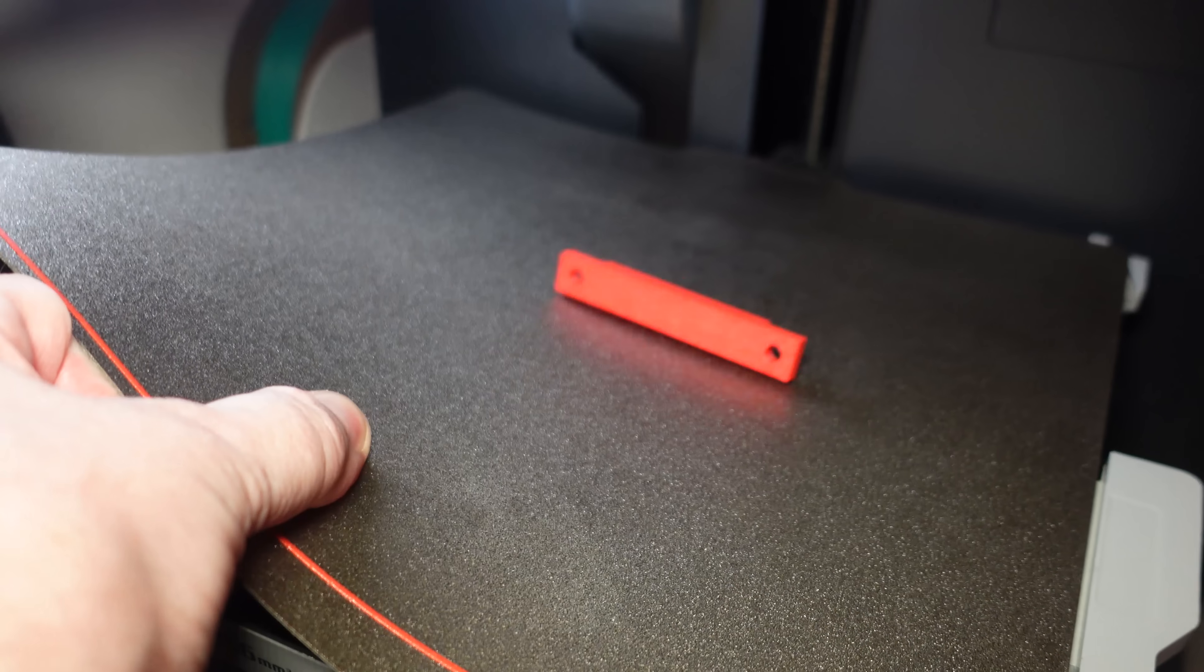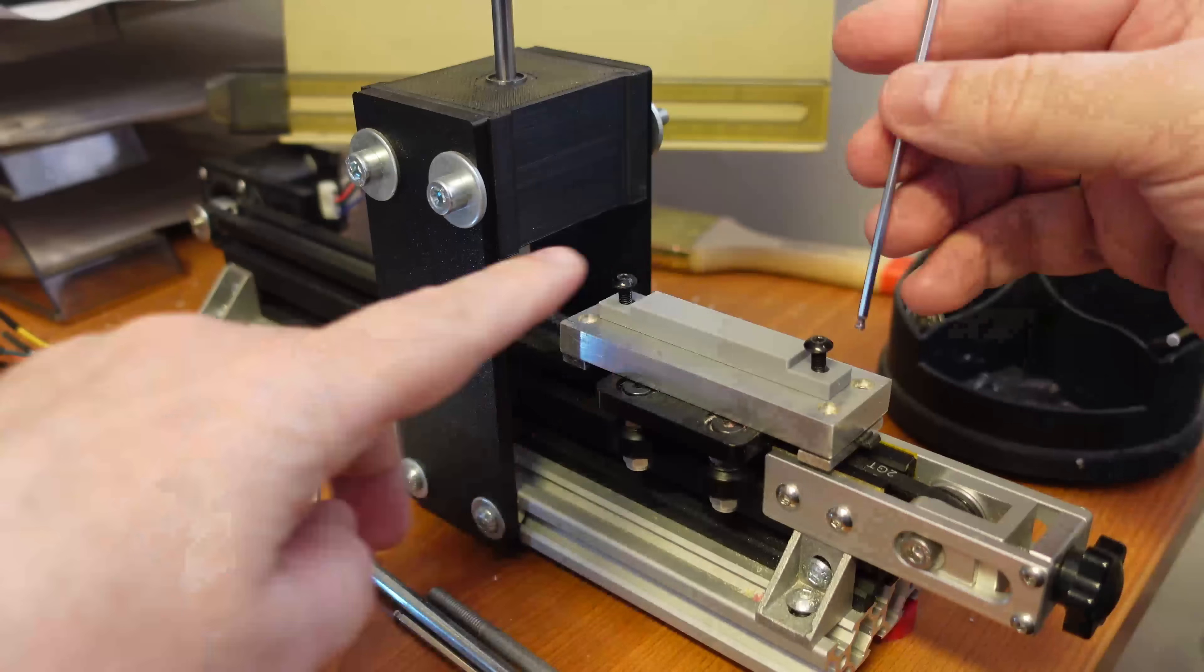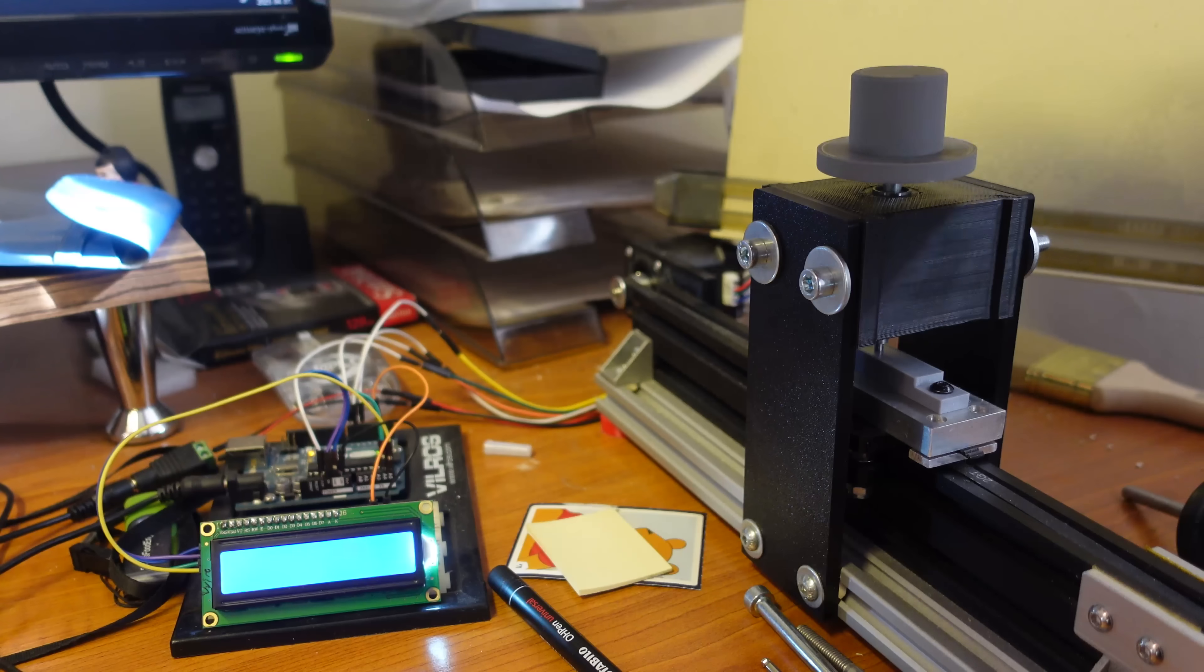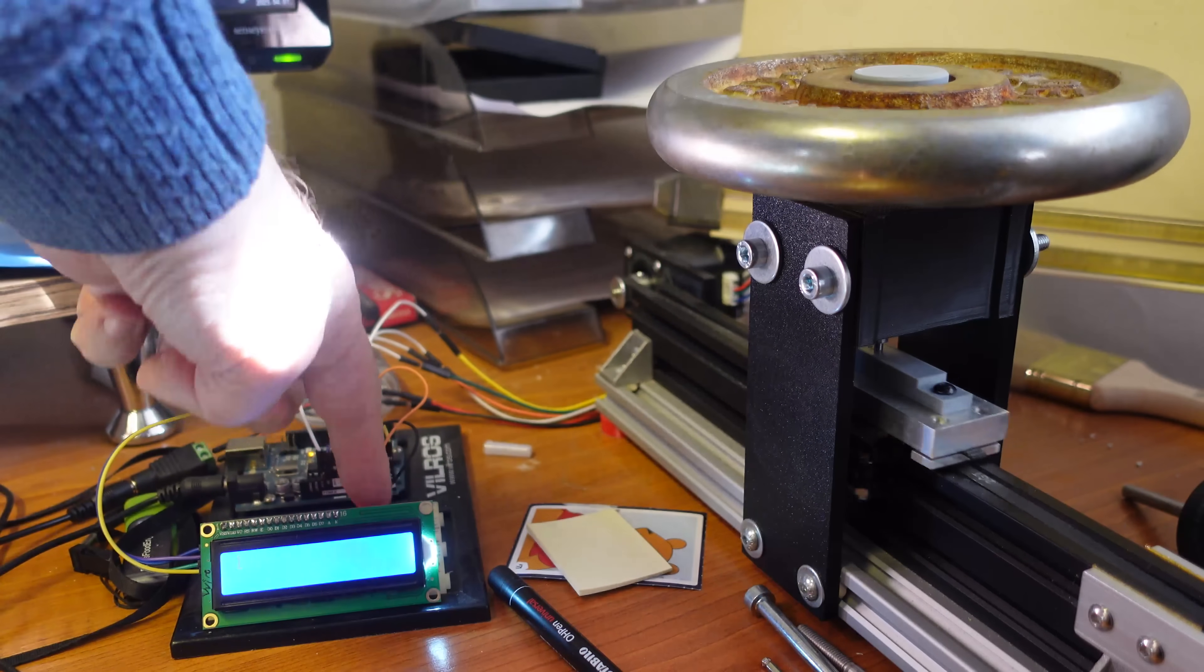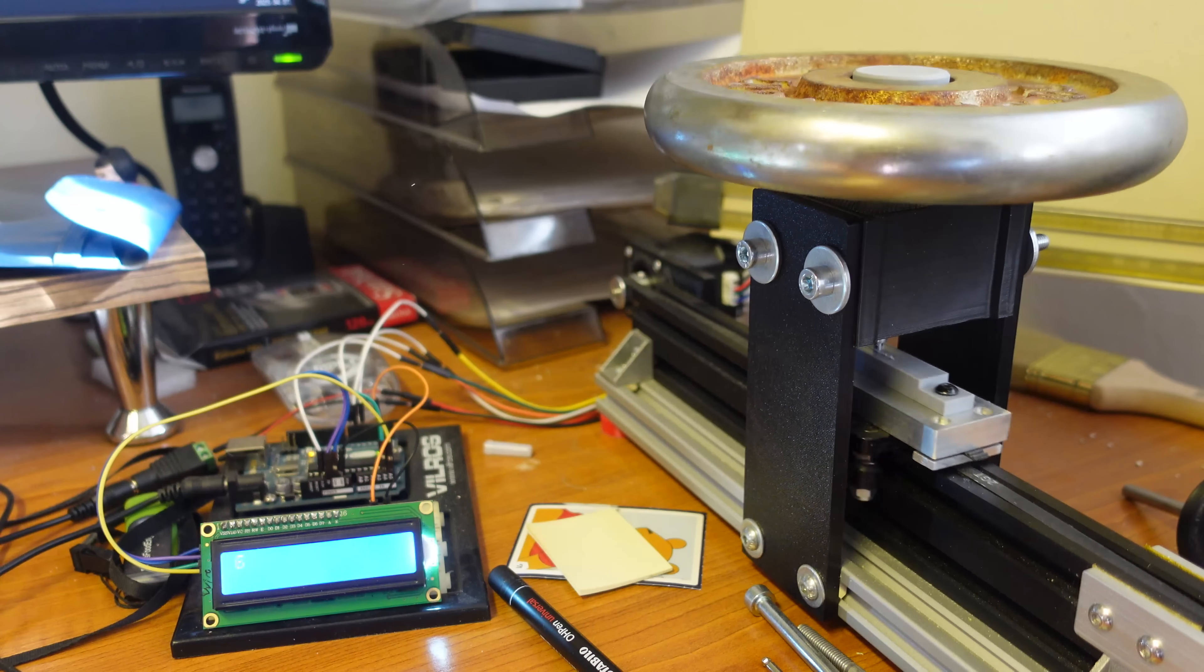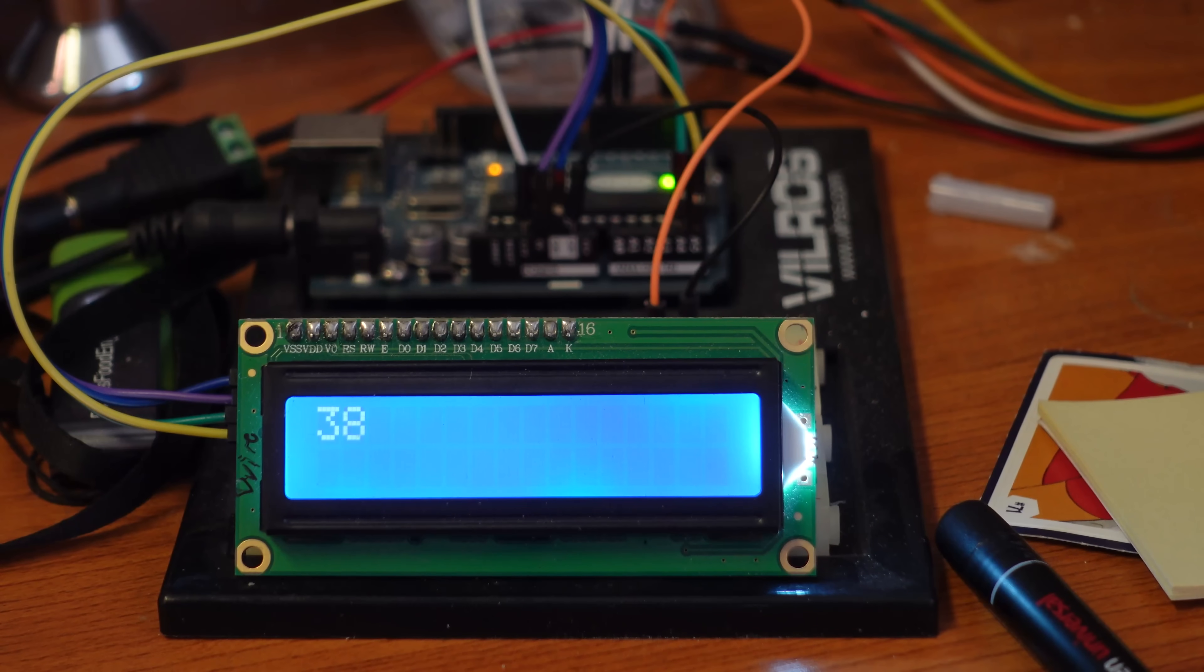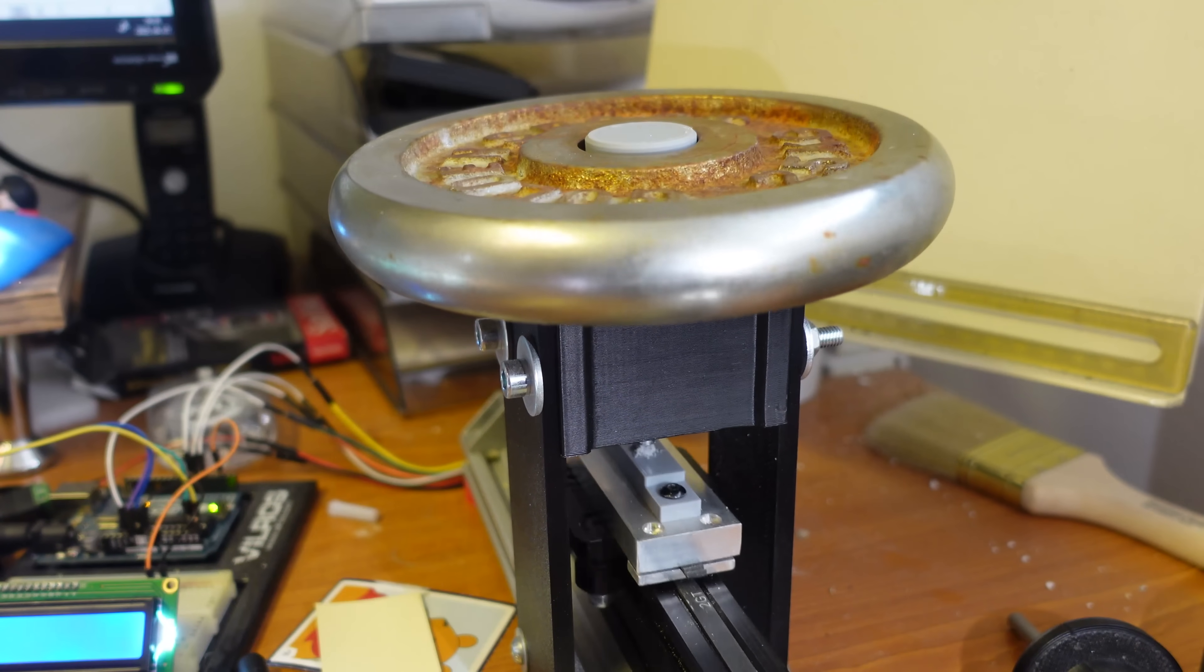And this object is for the wear test, and it will be compared again to the Polymaker PETG. I have a separate video where I explain this test. I'm using the smaller shaft, 3mm in diameter, and the weight is 2.5kg, and I will have exactly 100 repeats.